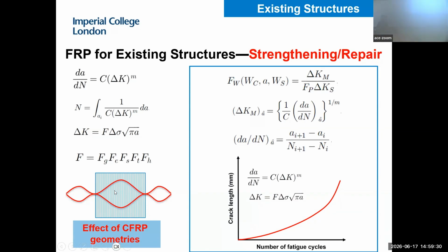Another effect we have to consider is that normally the FRP strengthening plate is smaller than your steel structure. Most of the time you cannot cover the entire surface of the steel structure—you can only cover a finite size over the crack location. So the red curve represents the crack behavior underneath the FRP material. Under the CFRP strengthening material, the crack will open underneath it, and because of the bridging effect, it will close at the tip. It will propagate, and eventually the crack tip will go out of the area covered by the CFRP material, and it will open again, because you don't have any material to bridge the crack edges.